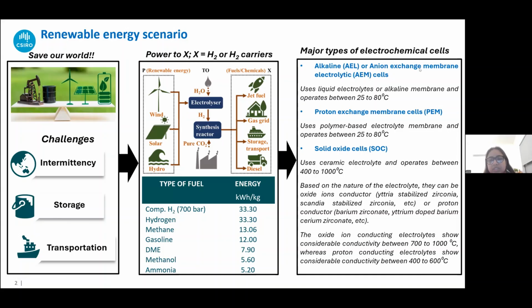Now, the major types of electrochemical cells include the low temperature regime and the high temperature regime. In the low temperature, we have the alkaline or the anion exchange membrane electrolyzers, which operate between 25 to 80 degrees. Then we have the proton exchange membrane electrolytic cells, which operate between, again, 25 to 80 degrees. And then in the high temperature regime, we have the solid oxide cells. Depending on what kind of ceramic materials we are using or the operating temperature, the solid oxide cells can be of two different categories.